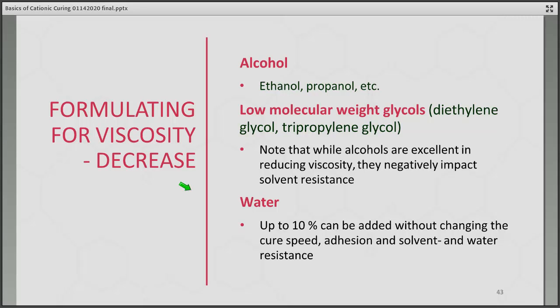And strangely enough, water can on occasion be used to dilute your UV curable cationic system. I know I just mentioned earlier that if you're using a UV curable system and want to increase reactivity, you may want to use a dry system. However, water can at times stabilize your UV curable formulation, and I've seen commercial applications in the past that intentionally added, say, 2% or 3% of water to make sure their line speed is consistent day in, day out, season in, season out. So you can use a little bit of water. I would be very cautious, though, about using much more than a few percent. I've seen it listed as up to 10% working well.